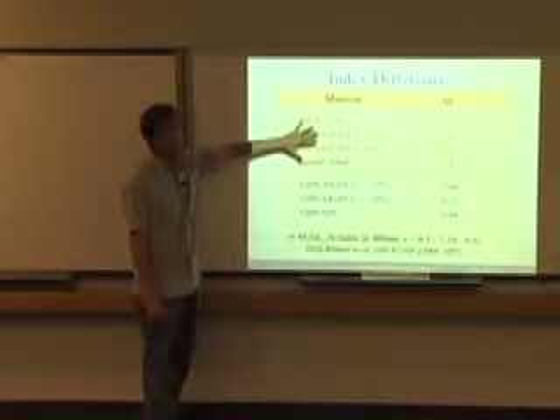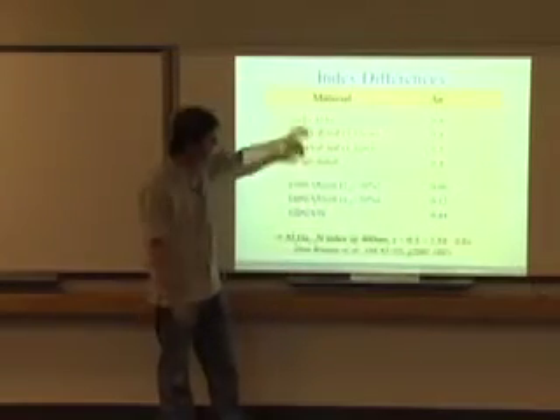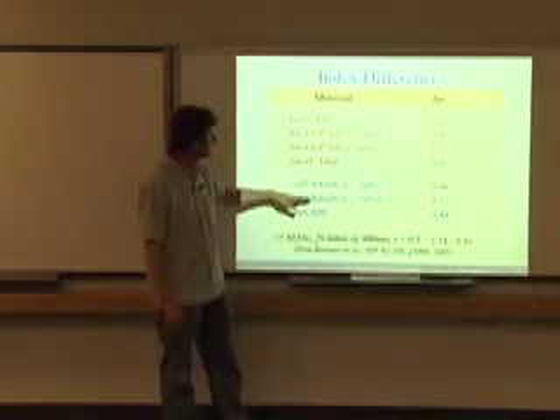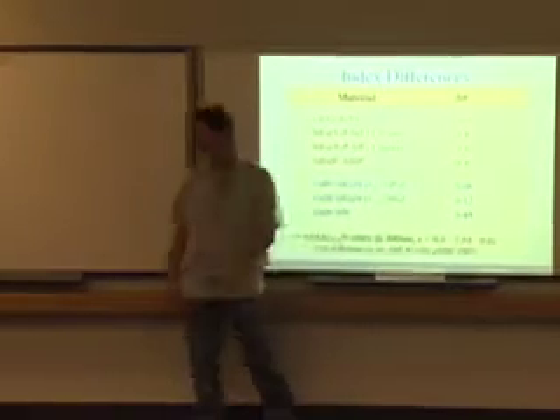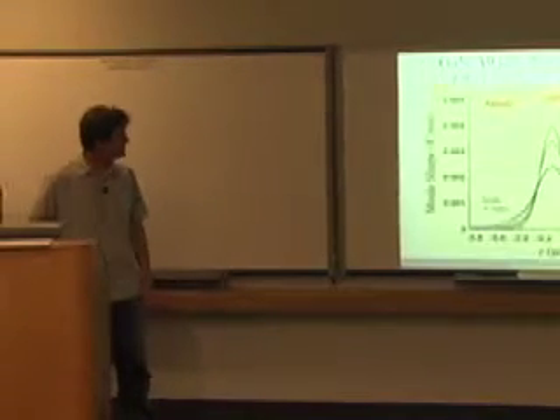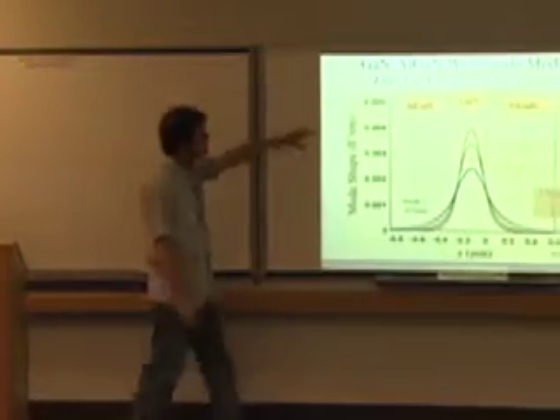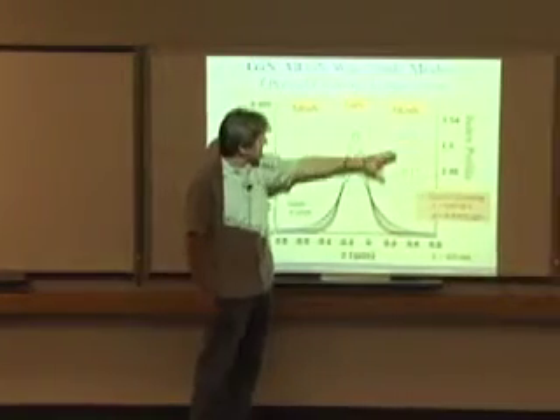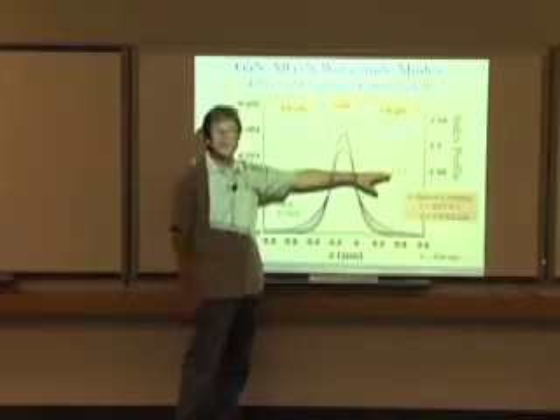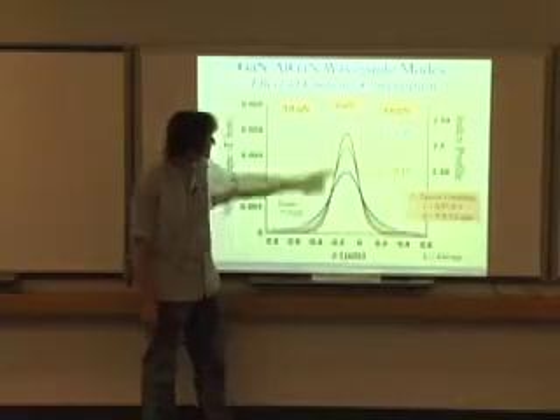And so if you then look at index differences of the different materials, again, the standard materials enjoy very large delta N's, and so you can make very nice waveguides vertically. In the AlGaN system, you really got to crank up the aluminum mole fraction. Even at 20%, you're only looking at 0.12 delta N. And so it's not very large, but nevertheless, you can still make confined modes with AlGaN. But you need to go up to, say, 0.15 aluminum mole fraction to get a decent mode.